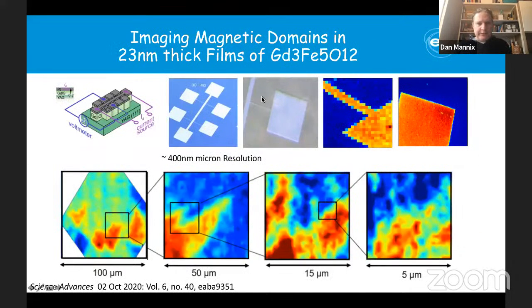So here I come into some of the results. I'm showing here the micrographs of our samples. This here is the starting diffraction data, the intensity of a Bragg peak. I'm looking at the sum of left and right. This is literally the scattering without looking into magnetic objects for the moment. The blue areas are zero because there's no film there anymore. This is just a substrate, and we're looking at the film Bragg peak, not the substrate Bragg peak. Then we scan around with the beam, and we can map out these structures very cleanly using this very small nanobeam on our device structures.